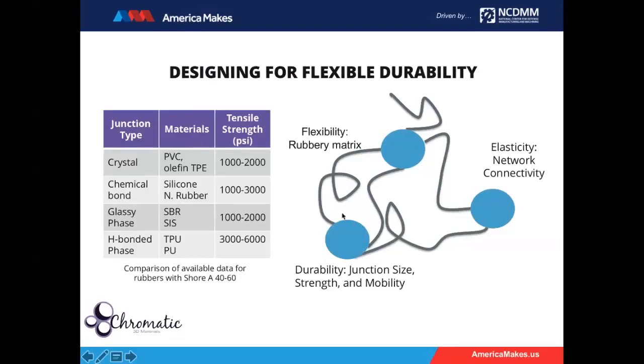So if we look at the library of flexible materials, we can see that with a variety of different hard segments or junction points, you can access a wide range of tensile strength. This is just looking at a library of materials with a Shore A flexibility of 40 to 60. In this range, you might find PVC or olefin thermoplastic elastomers. In those cases, the junction that gives the material elasticity and strength is a polymeric crystal, and the tensile strength tends to be between 1,000 and 2,000 psi. If you have chemical bonds linking these gray pieces together, like silicones or natural rubber, the tensile strength can range from 1,000 to 3,000 psi.